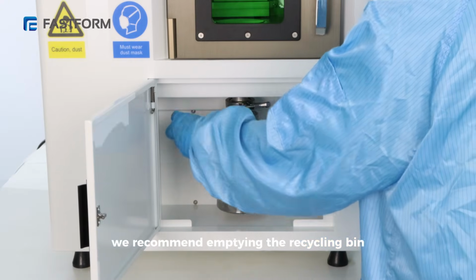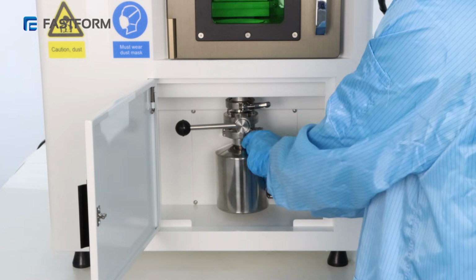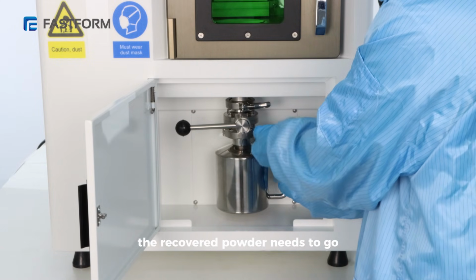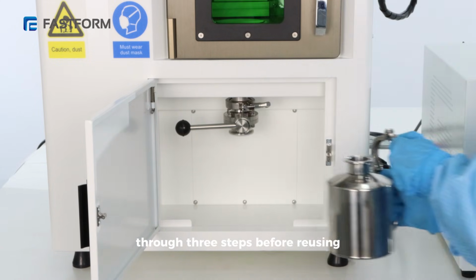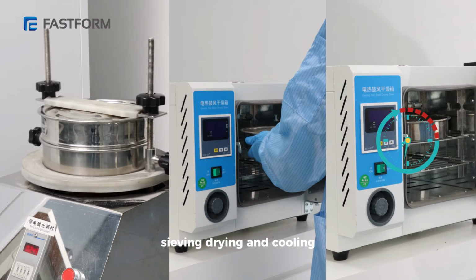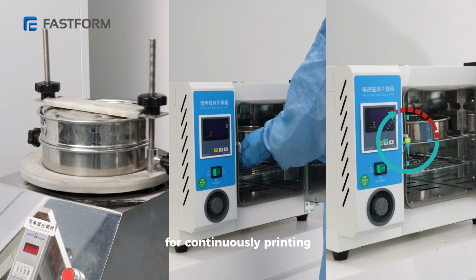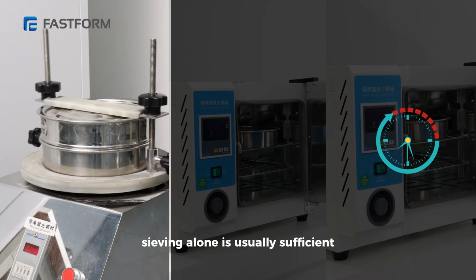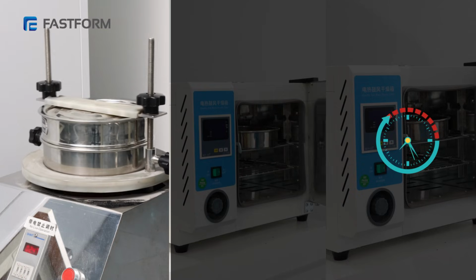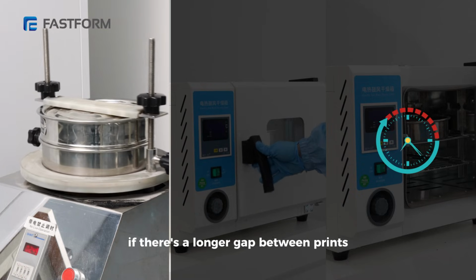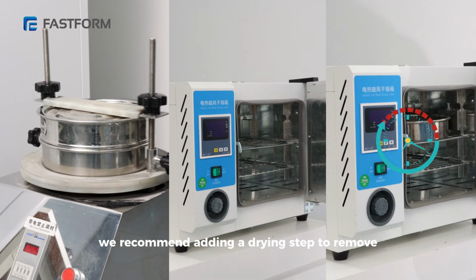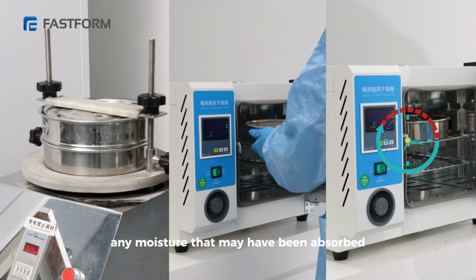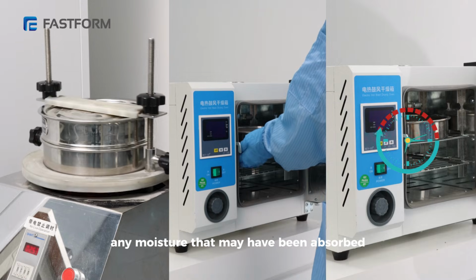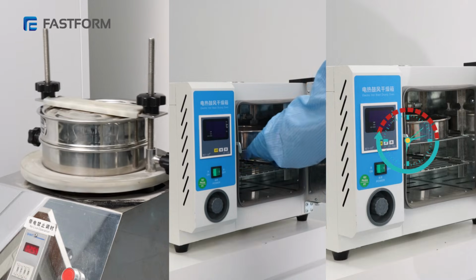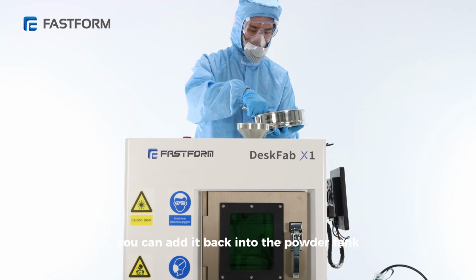After each print, we recommend emptying the recycling bin. The recovered powder needs to go through 3 steps before reusing: sieving, drying, and cooling. For continuous printing, sieving alone is usually sufficient. If there's a longer gap between prints, we recommend adding a drying step to remove any moisture that may have been absorbed. Once processed, you can add it back into the powder tank.